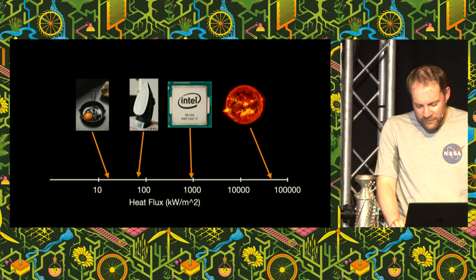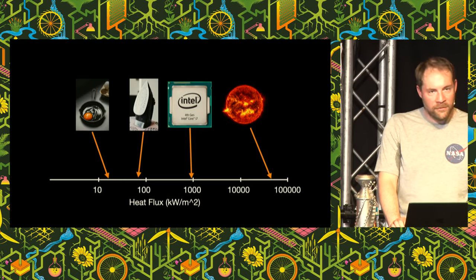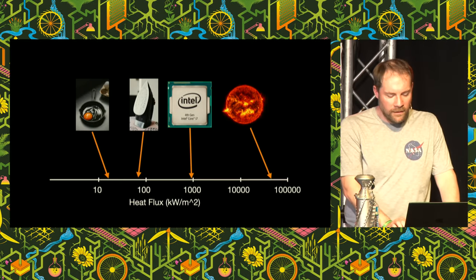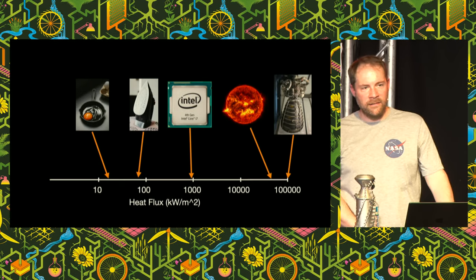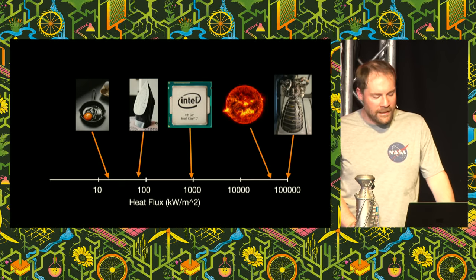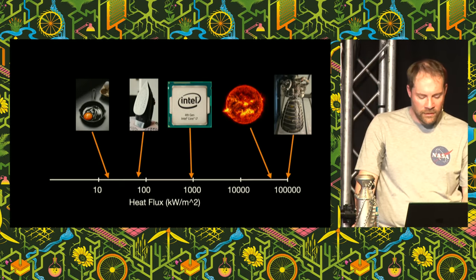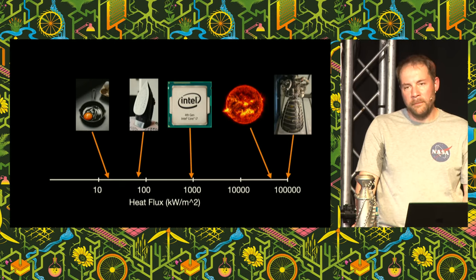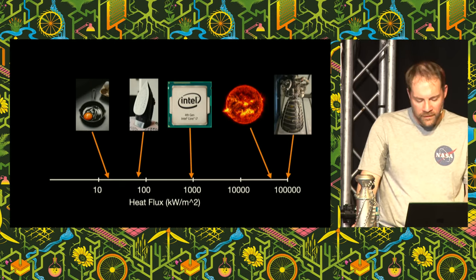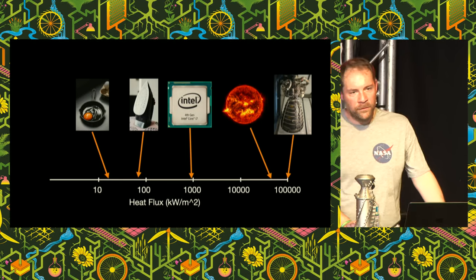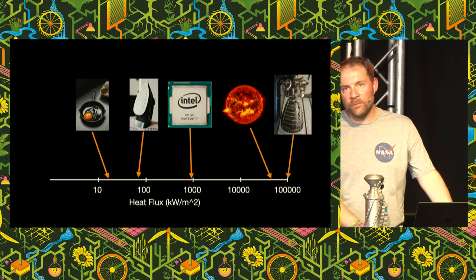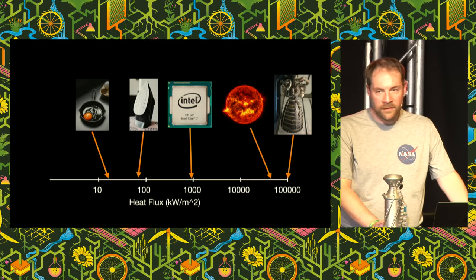So that's up at about 50 megawatts per square meter of heat flux. And then finally, we reach our engineering problem, a rocket engine, where the heat fluxes into the wall are typically 100 or even hundreds of megawatts per square meter. So it really is an extraordinarily difficult cooling problem, and it's really one of the central problems for designing a rocket engine: just how to stop it melting.